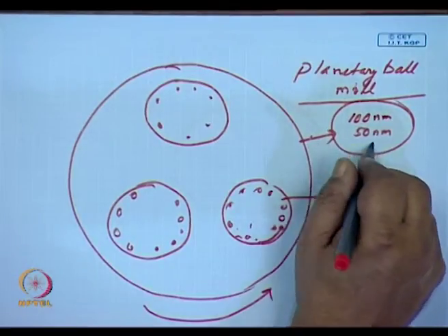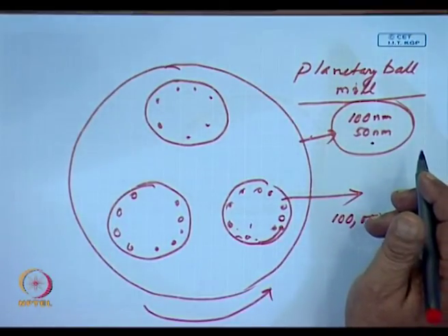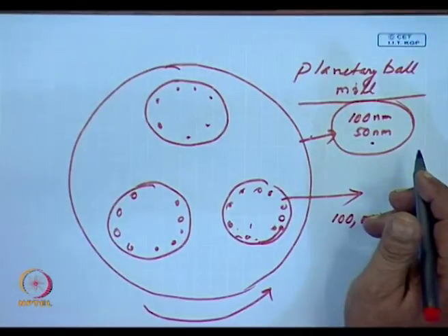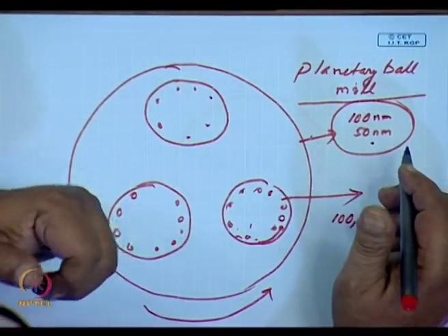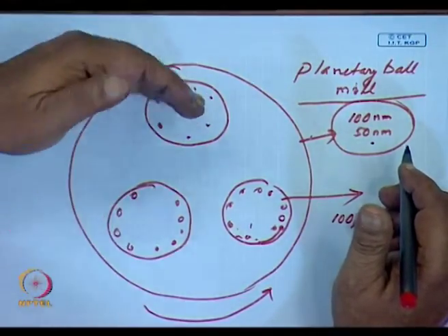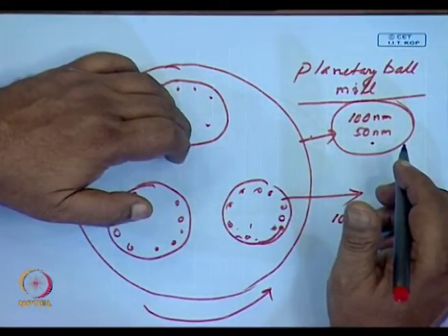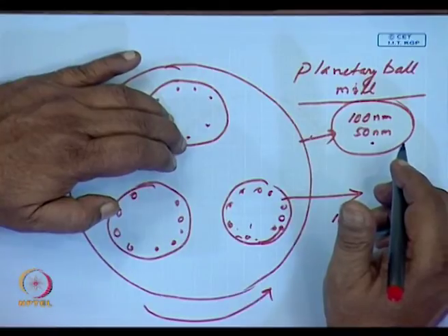You have to understand, we started off from large grains, maybe the grains of sand, and from here we are coming to submicron range where the surface energy is very high. So here during this comminution, erosion, corrosion and hence contamination plays a very, very major role.